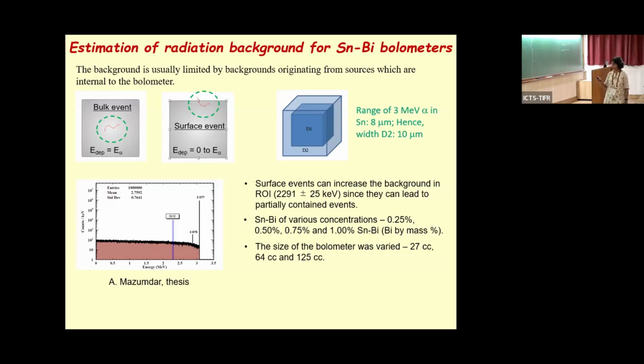So we did some simulations and showed that we need about 0.22% of bismuth, but even at 0.25%, the background is handleable. Now here again, the size of the bolometer becomes important, because if I make a larger crystal, say a cube of 5 by 5 by 5, then the surface to volume ratio is better, so I will have an overall higher efficiency. But if I have a bulkier detector unit, then the net temperature rise for the energy deposition, because mass is large, will be small. So you need to make an optimization between the two, and 5 cross 5 cross 5 seems to be a reasonable size for that.